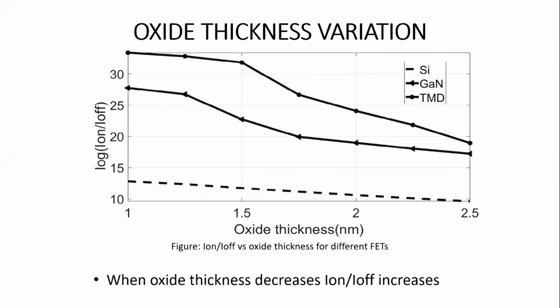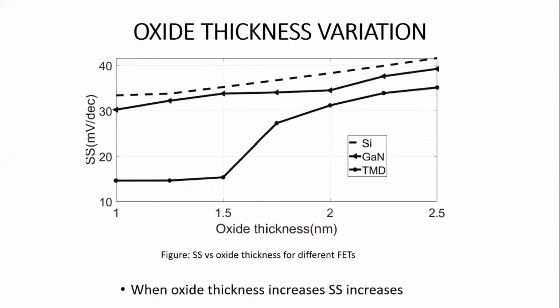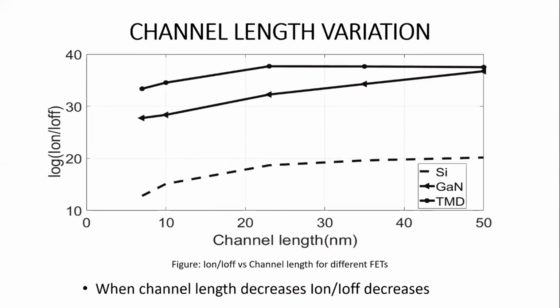Now, here you can see when oxide thickness decreases, Ion/Ioff increases. Here is the value for oxide thickness variation for subthreshold swing. We can see when oxide thickness increases, subthreshold swing increases. I forgot to say, we used silicon, gallium nitride, and TMD as materials for channel material.